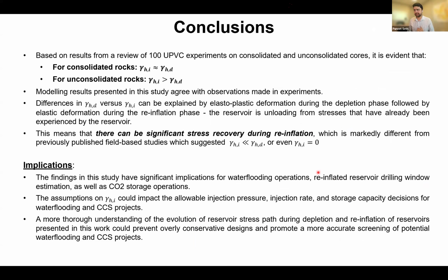and unconsolidated cores, it was quite clear that for consolidated rocks, the injection and depletion coefficients are very similar, sometimes even exactly the same. And that's because in harder consolidated rocks, it is elastic deformation that dominates. In softer unconsolidated rocks, the injection coefficient can actually be higher than the depletion coefficient. The reason is plastic deformation. Depending upon how much you deplete the sample, plastic deformation can dominate. And when that happens, the depletion coefficient decreases, as you saw with that curving in the example that I showed previously.